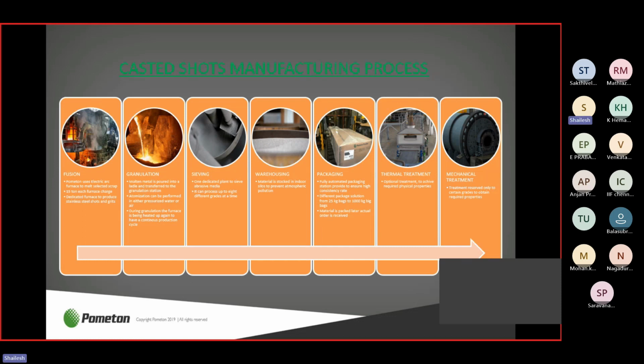Why do we do thermal treatment? Thermal treatment is required just to achieve the proper hardness of the shots. After granulation, we quench it in water, where the hardness becomes very high, close to 50 to 55 HRC. But sometimes we don't require that much hardness in stainless steel shots, so we do thermal treatment to bring the hardness down to 45 to 50 HRC. This is not done for every grade; only for certain grades of stainless steel shots do we do thermal treatment to achieve the hardness.